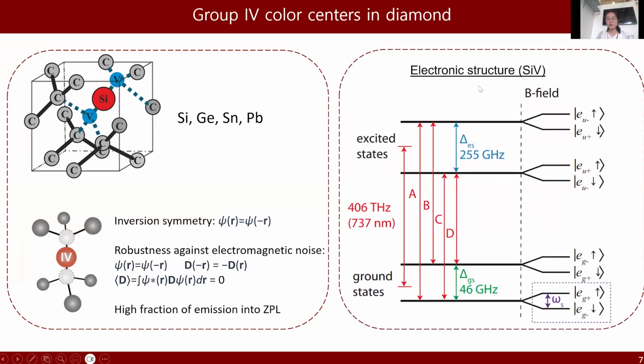The right figure shows the electronic structure of the silicon vacancy center. It has 2 ground states and 2 excited states, both of which are split by spin-orbit coupling. Other types of group 4 color centers will have a similar electronic structure, but with different spin-orbit coupling strengths. So for SiV, this ground state splitting is 46 gigahertz, but for GeV, this number is 160 gigahertz.